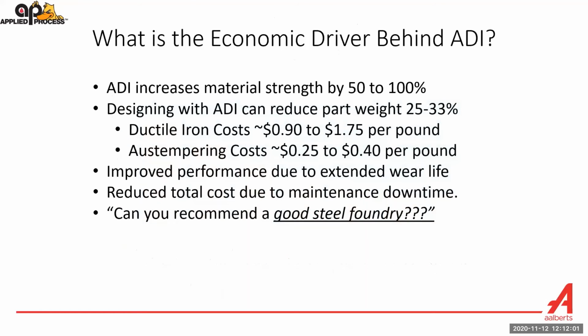So what's the economic driver behind switching parts from, say, a fabrication or a forging to a ductile iron casting that's Austempered? Because ADI increases the strength of the material by 50 to 100% or more, now you can reduce the part weight. And that is where the power is. It's design optimization. Ductile iron costs typically, it varies a little bit, but 90 cents to $1.75 per pound. And if you can reduce the weight by 25 to 33%, now you can come back and Austemper the part and have a net neutral part, perhaps, from a cost perspective.